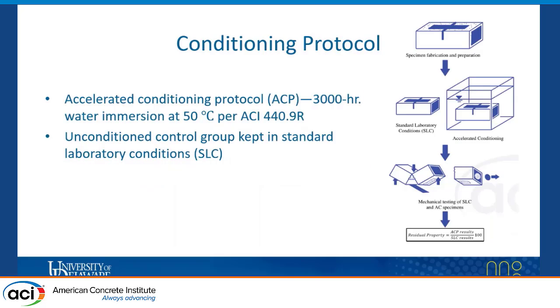The accelerated conditioning protocol that was selected for this study was in accordance with ACI 440.9R, which suggested immersing the strengthened beams in water at a constant temperature of 50 degrees Celsius for a duration of 3,000 hours. The accelerated conditioning protocol group, I'll refer to as the ACP group. In addition, there needs to be an unconditioned control group that's held in standard laboratory conditions, and we'll refer to that as the SLC group.